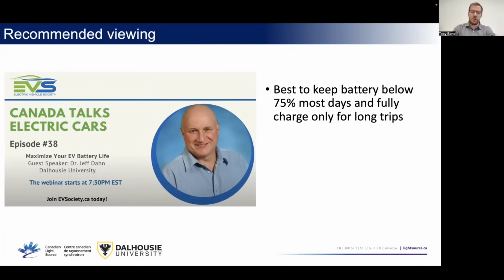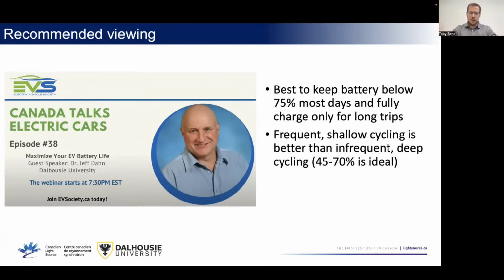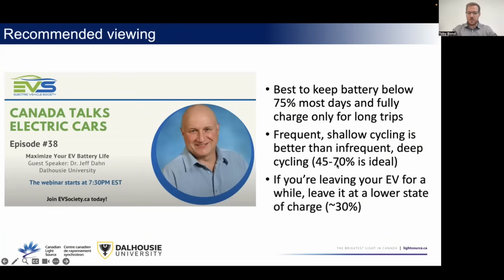It's best to keep your battery below 75% if you have an NMC or NCA battery pack, which is most battery packs in North America, because it limits the voltage, keeps it lower, and also means you don't expand and contract the electrode as much. On the same note, if you can do more frequent charging and discharging rather than infrequent but deep charging and discharging, that's better, again because it limits the amount of volume change and limits that fatigue. Something between 45% and 70% state of charge is ideal.